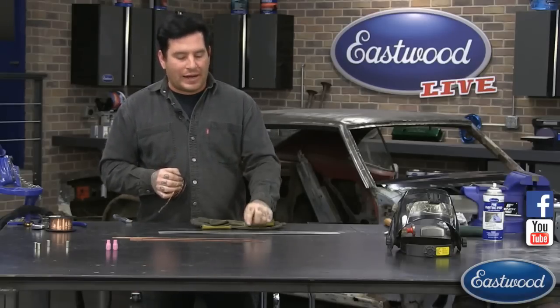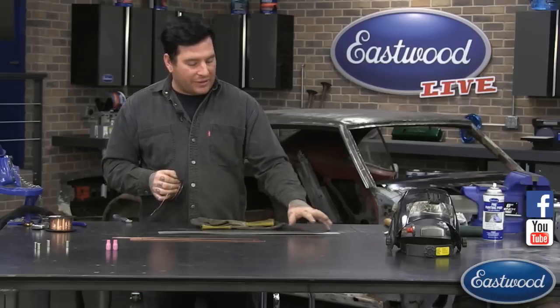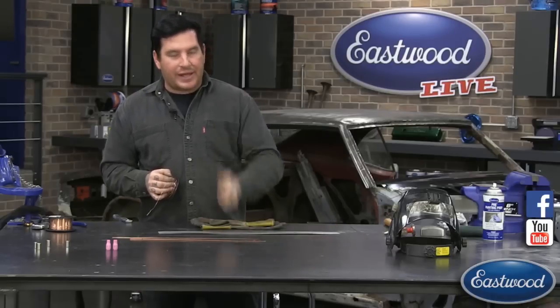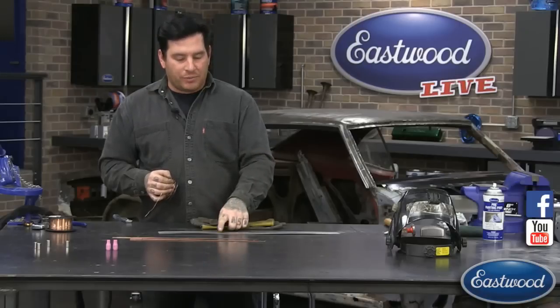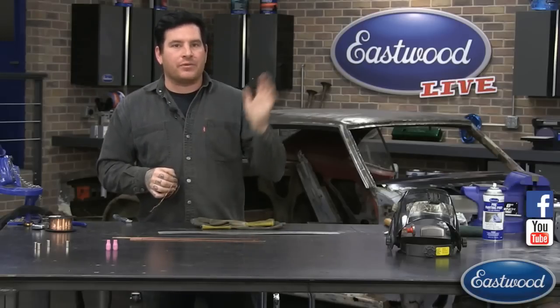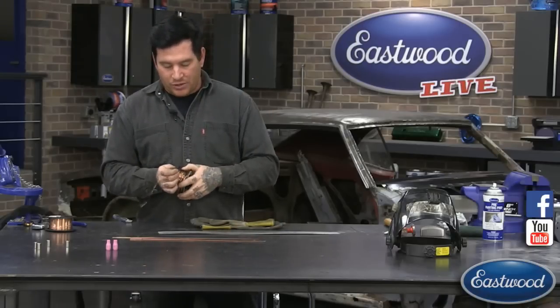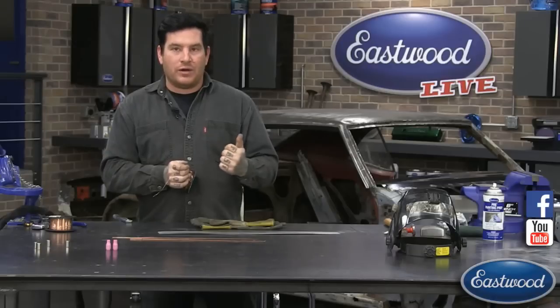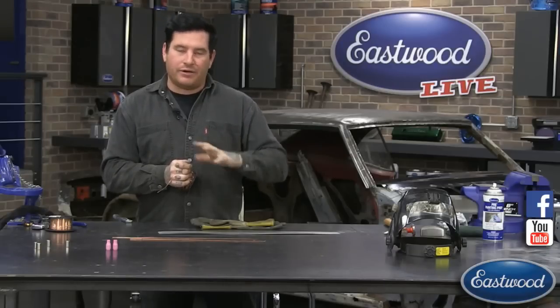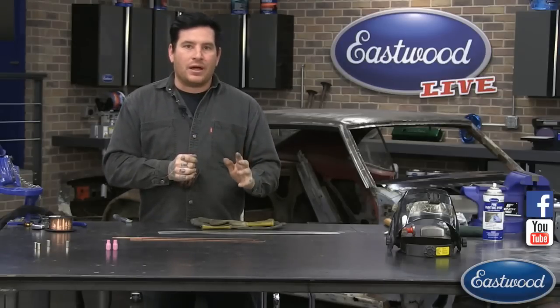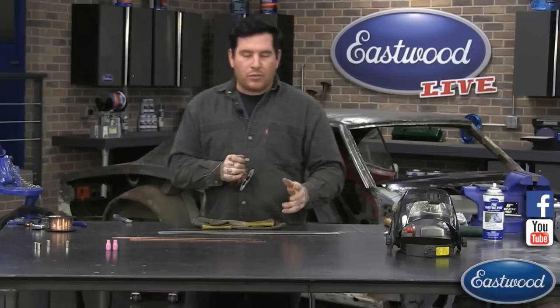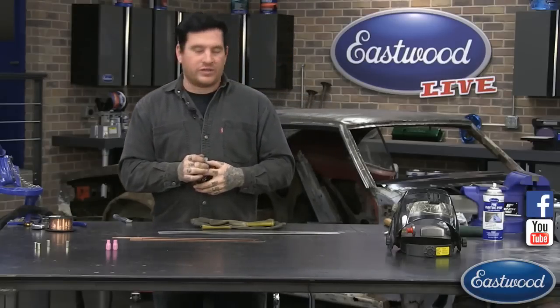If we were doing this to the same panel that we tack welded with a MIG welder and I hammered it on dolly like that, you would have probably seen these welds start to separate and they would have popped loose from the panel. So you can planish a TIG weld, which means you can hammer and dolly it and smooth it out and manipulate it. Where a MIG weld, you get what it is. You can't hammer and dolly the weld too much, or it does crack.